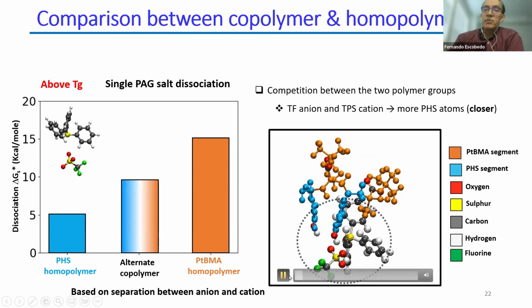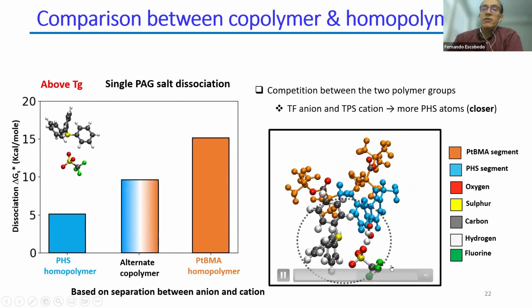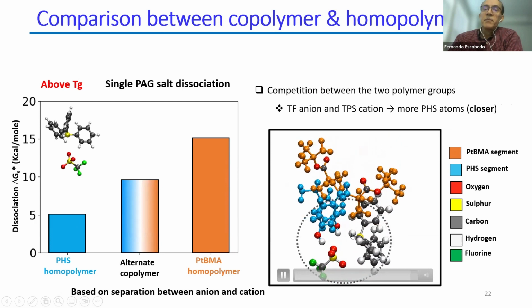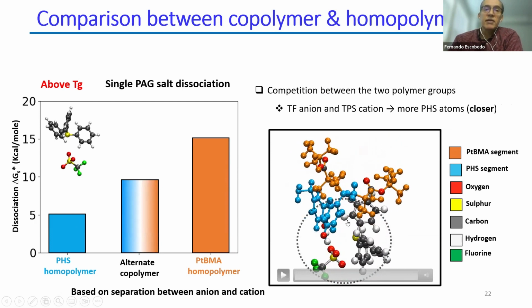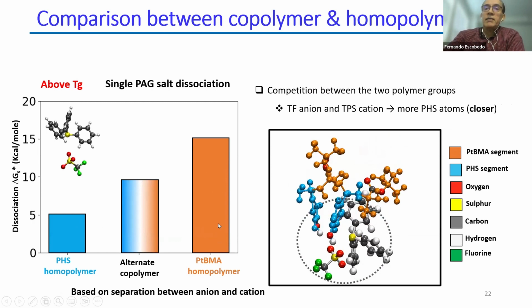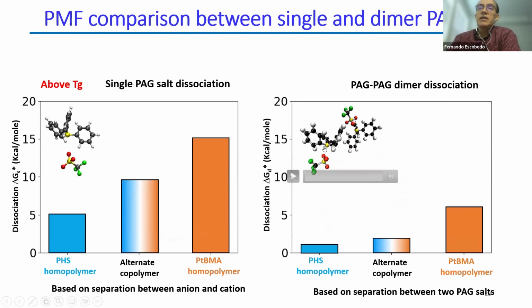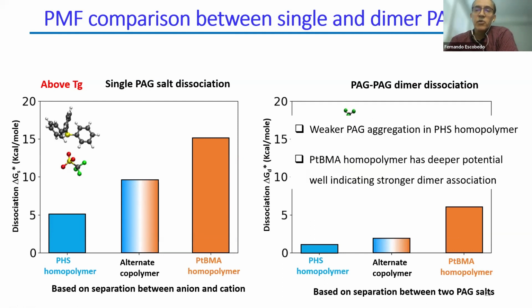And when you look at some of the conformations of how the ions in the salt interact with these polymers, there is a preference for them to interact with the polar group of PHS, not so much PTBMA. Similar results are seen for the case of two salts dissociating. The values of the barriers are smaller, as you can see, but you see a similar trend where PTBMA will be the worst host for dispersing this salt, and hence you would expect more association in PTBMA.